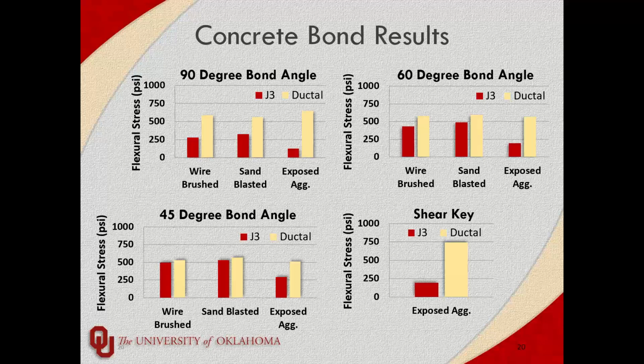And I'll bring this up later, but we did notice that the compressive strength didn't really affect some of the important properties as much as we would have thought. But I'm pretty sure the FHWA was also considering lowering that compressive strength, because I don't think ours was a unique problem, and a lot of studies using these locally available materials had issues reaching those high strengths. And I think it has a lot to do with the cements that are locally available. It all just depends on where you are in the United States.